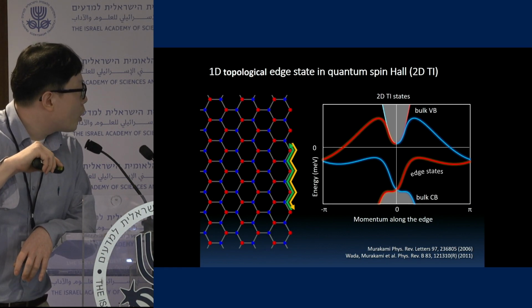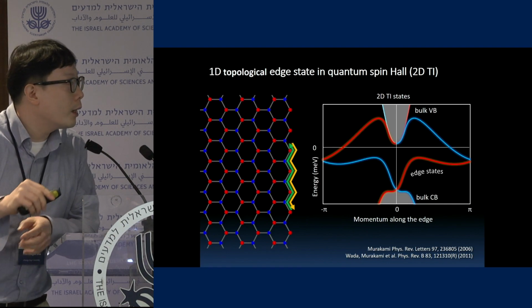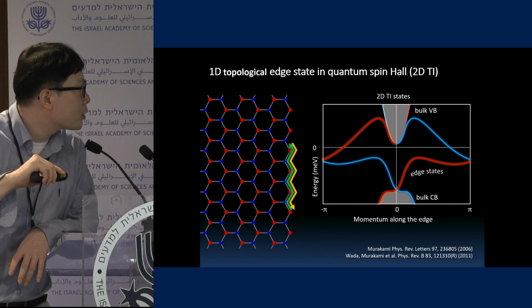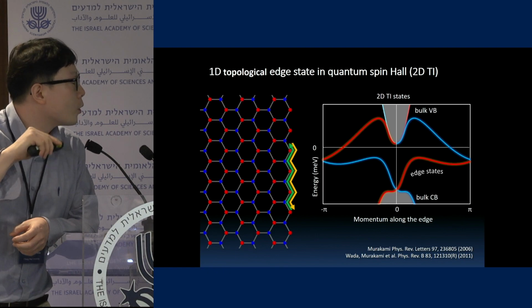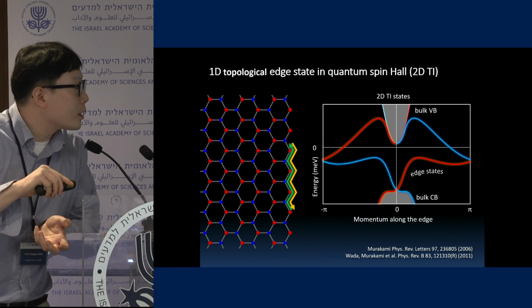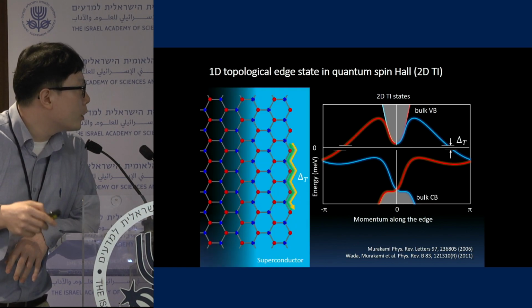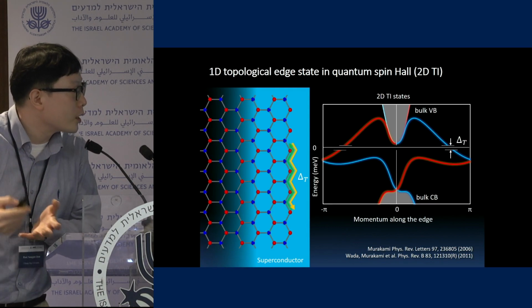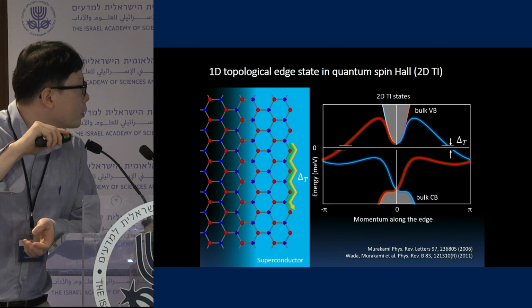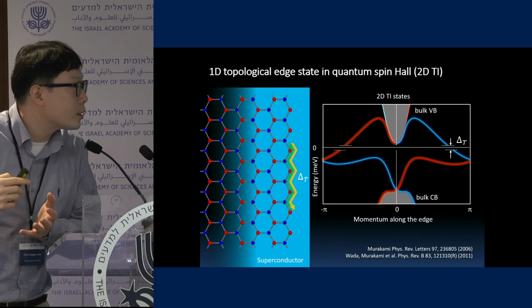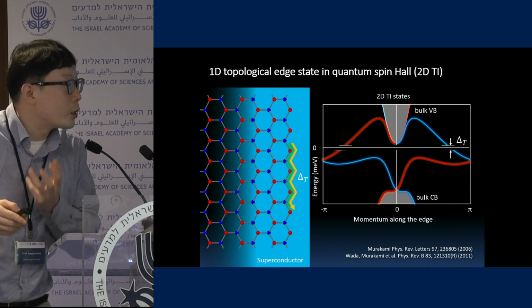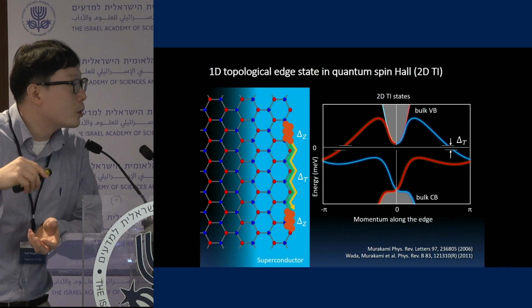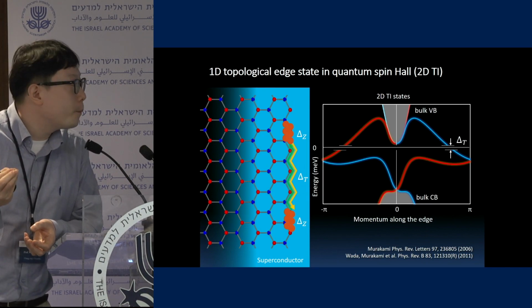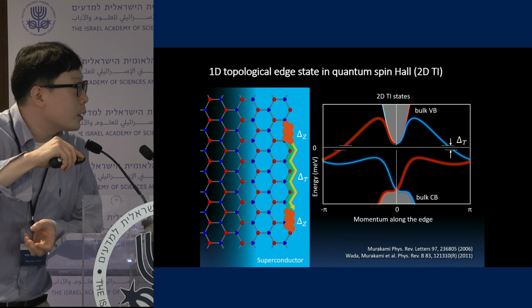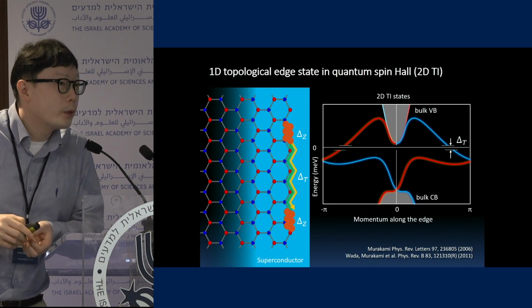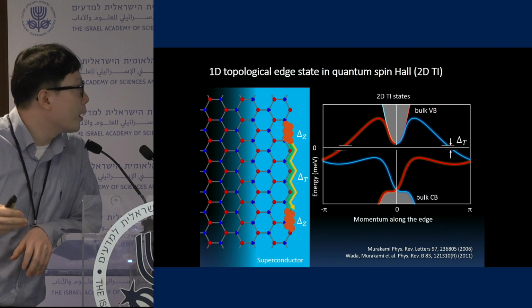So let's assume that this is a quantum spin Hall system or two-dimensional topological insulator system. And then you will get boundary states. And these are helical boundary states, with very strong spin-orbit coupling. One is going around here and the other is going around this way. So this is one-dimensional and spinless system as mentioned. And then we wanted to induce the superconductivity on this kind of electronic states. Of course, by doing this, this topologically non-trivial state is going around this two-dimensional system. So we need proper termination to get the zero end state. So this is how we actually put some magnetism to get a topologically trivial gap. And then this is the topologically non-trivial side. So you can expect to see the interface state at the interface here. That is our original idea to realize the Majorana zero modes in here.